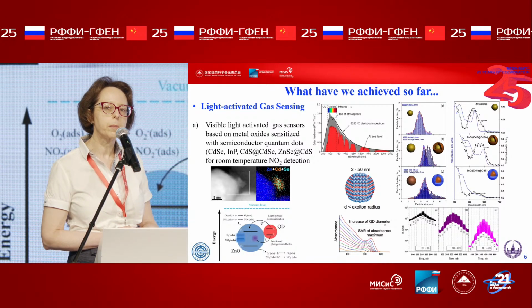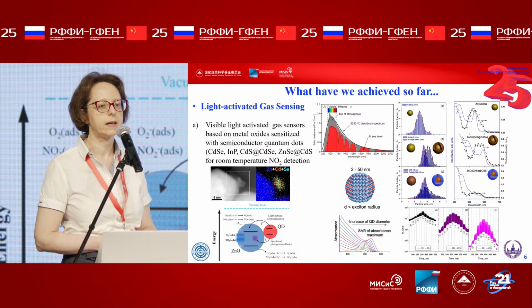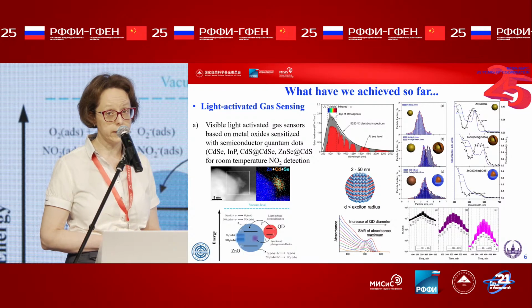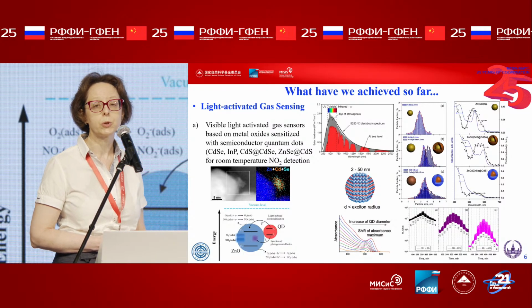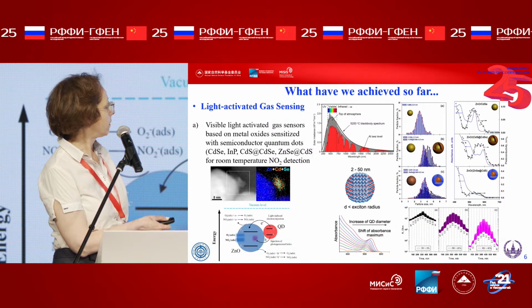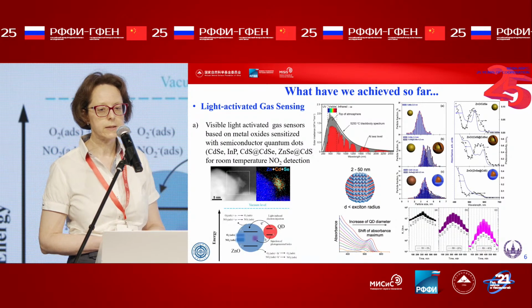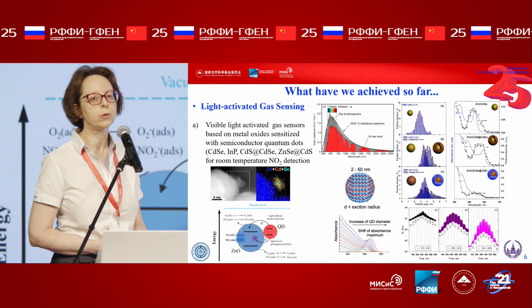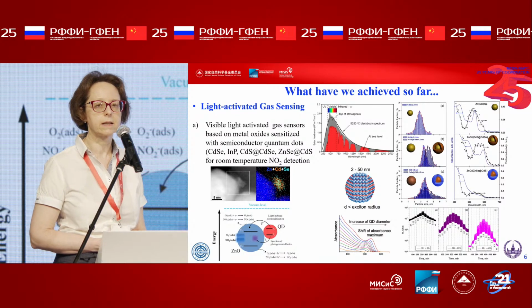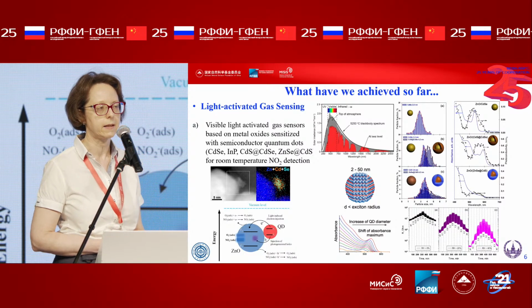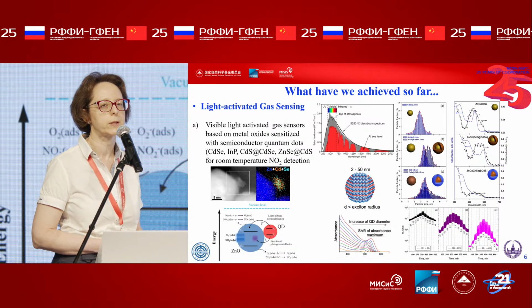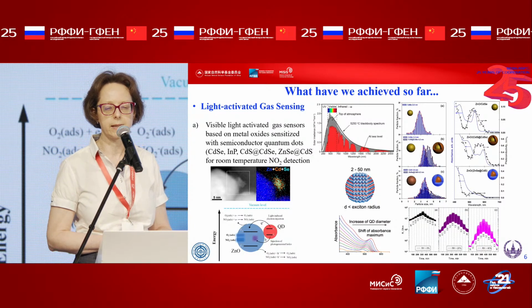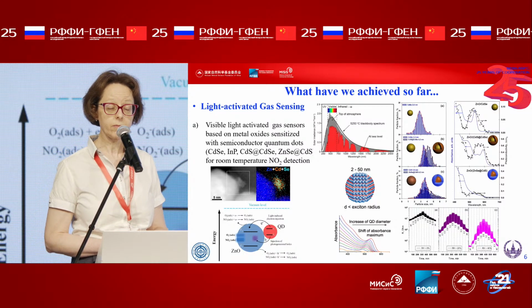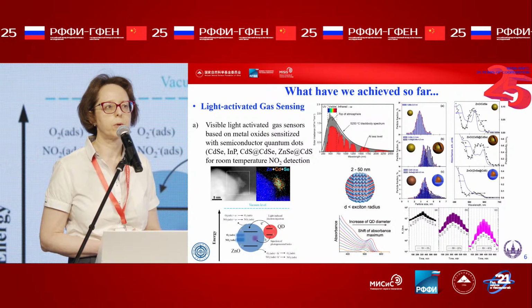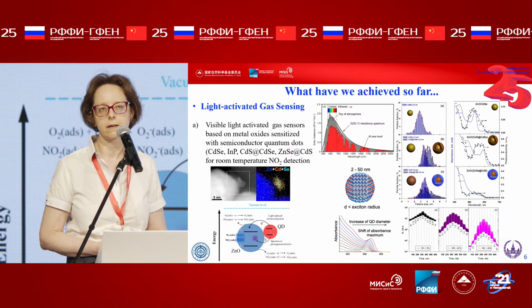So to activate them under visible light, it is necessary to add some photosensitizers, which can be organic dyes or semiconductor quantum dots. Semiconductor quantum dots are nanocrystals with a diameter of several nanometers, and their optical properties are strongly dependent on their size. So we synthesized the nanocomposite containing wide gap semiconductor oxides like zinc oxide, tin oxide, indium oxide, and semiconductor quantum dots like cadmium selenide, indium phosphide, and also core shell heterostructures made from cadmium sulfide, cadmium selenide, and zinc selenide, cadmium sulfide.